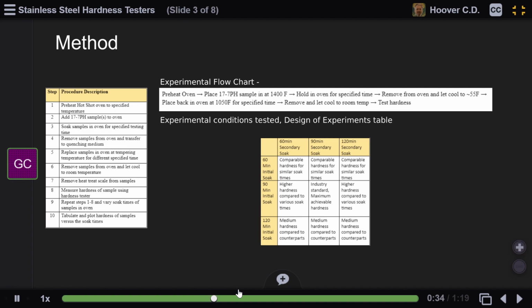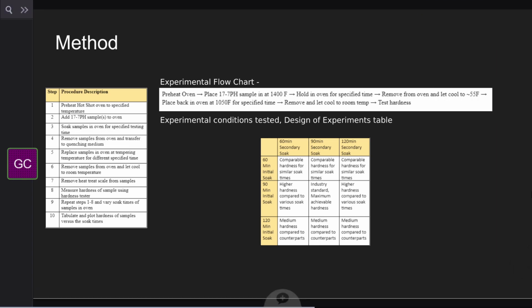Once that time passes, place the samples back in the oven at a lower temperature for a different specified time. Once they reach that, again we remove them and let them cool to room temperature for the final time. After they're cooled off, descale them and bring them over to our indenter and measure the hardness of each sample. Repeat steps 1 through 8 and vary our soak times of the samples in the oven to see if we can get harder or less hard samples, and see if there's an optimal recipe.